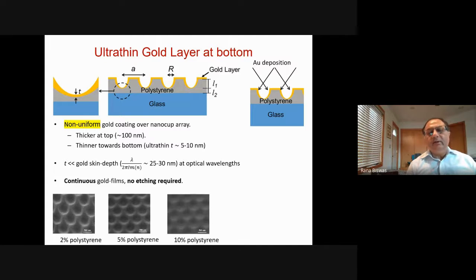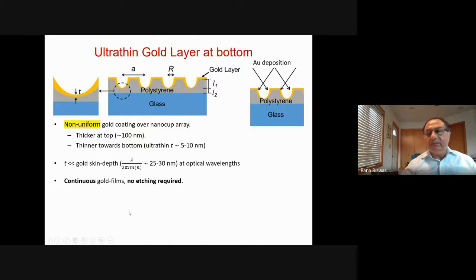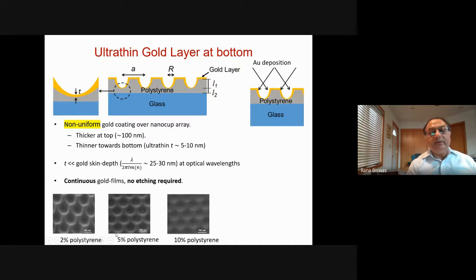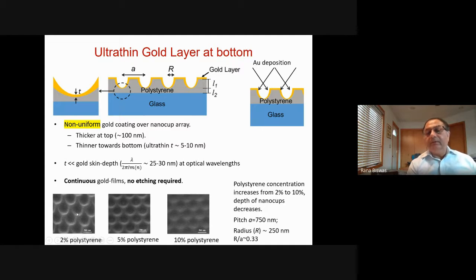And you can see the results for the different polystyrene concentrations in solution. So as you increase the polystyrene concentration from 2 to 10%, the depth of the nanocups decreases. The pitch, of course, stays the same at 750 nanometers, and the radius is about 250 nanometers. So the pattern is best defined for the low concentration of polystyrene.